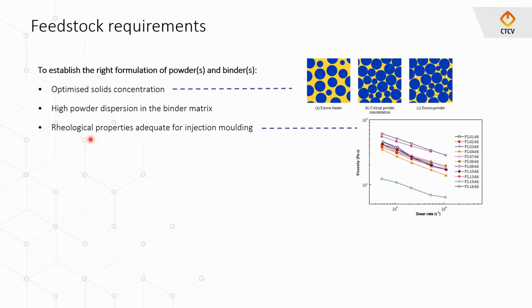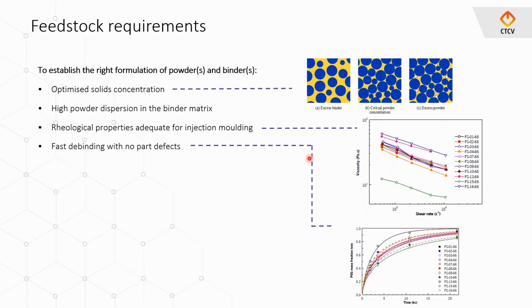We have to have rheological properties adequate for injection molding. Usually, we can find this relationship between the viscosity and the shear rate, and we are talking about pseudoplastic behavior of the compounds. And of course, we have to plan for a fast debinding with no part defects. So when we are developing the binder, we have to keep the debinding in mind as well, to avoid part defects and to speed up the debinding as much as possible.